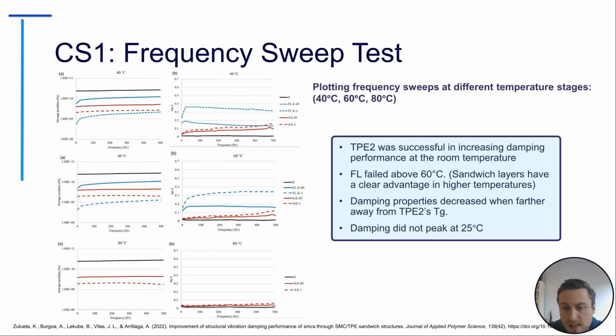However, they noticed too that the damping properties decreased the further away they got from the thermoplastic elastomer's Tg, which is expected as well, since the material will not have a high tan delta, therefore won't have a high damping factor.